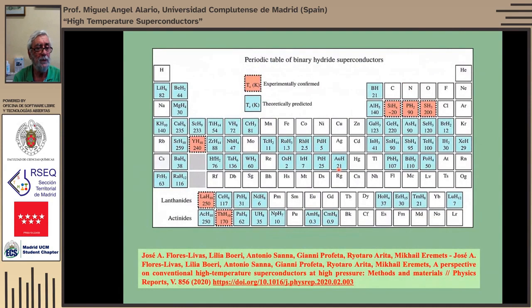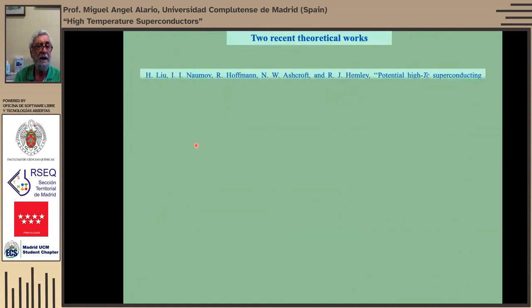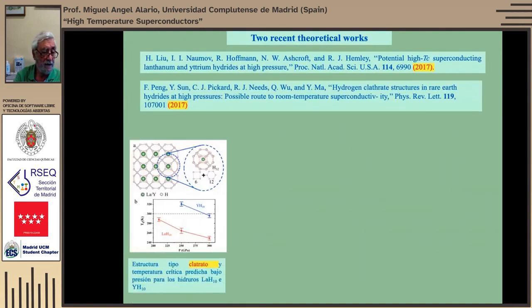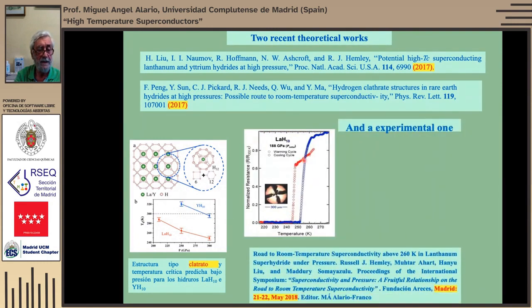Now, this is really two more slides, I think. This is the periodic table of binary hydride superconductors. These are the critical temperatures which have been calculated, and these are the experimental. You see the highest are this one, which has been experimentally confirmed, and this one, which hasn't yet been confirmed, although there are data. So there are two recent works. One is lanthanum H10 and yttrium H10. Yttrium will be the highest, and then experimental data, this is the lanthanum, which has been confirmed. This hasn't yet been measured.